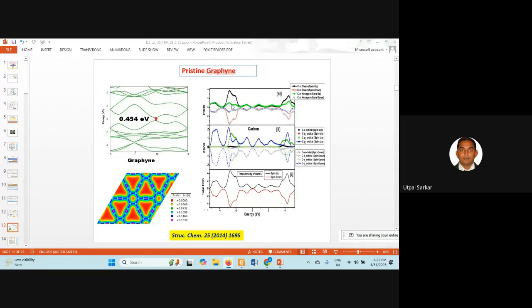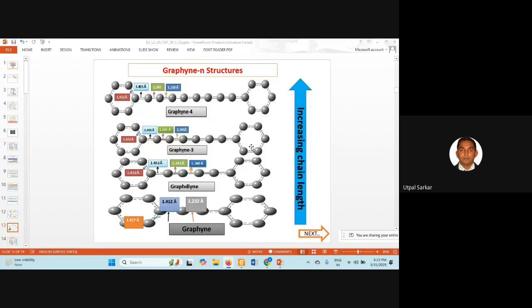However, in the valence band, at a deeper point, let's say around 3 electron volt, the chain site contribution is much more than the ring site contribution. And you can characterize which particular orbital is contributing near the Fermi level, as well as throughout the energy range you are considering. Here it is the pz orbital of the carbon atoms that are basically contributing near the Fermi level.